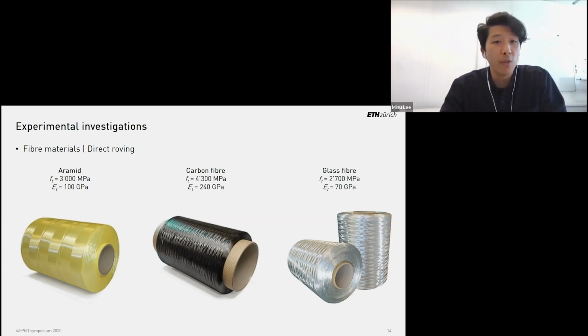Carbon and glass fiber rovings are much more brittle and sensitive to lateral loading, and they therefore do not allow for small bending radii. So they can even be broken by hand when you fold them sharply. But in the reinforcement patterns with straight inlays, all 3 materials were examined.